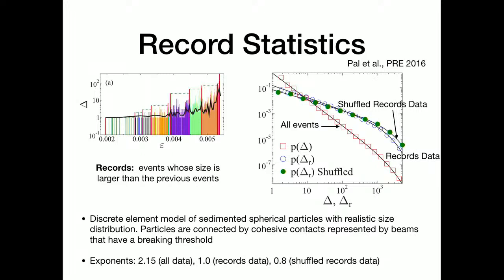So from 2.15, which was the exponent for the, okay, I didn't mention what study this is. This is a simulation in which you have spherical particles, three-dimensional. You make a cylindrical sample with sediment and spherical particles, and the size distribution is the disorder. And I couldn't follow exactly how they have put their fracture behavior, but the disorder seemed to be part of the size of the particles. Anyhow, what they report is that they see the power law behavior in the all data and the records data, but the power laws are different.